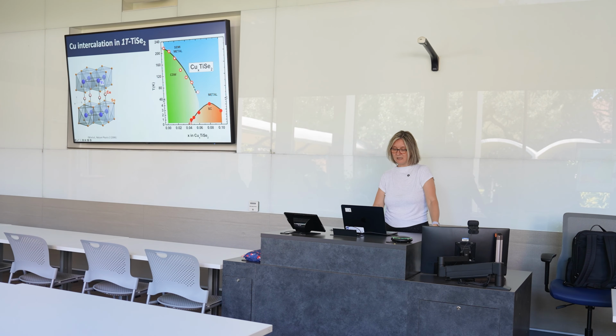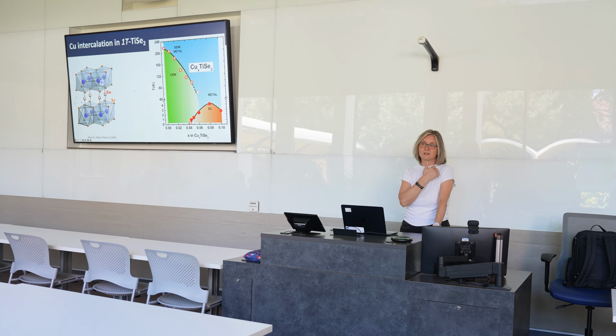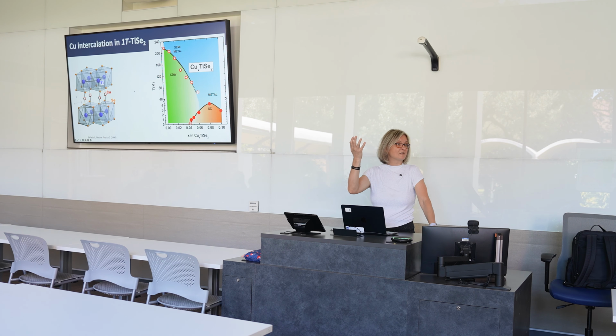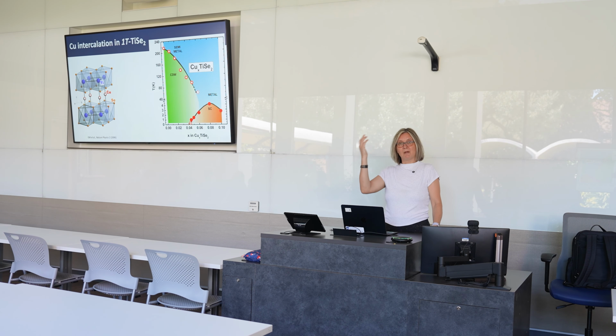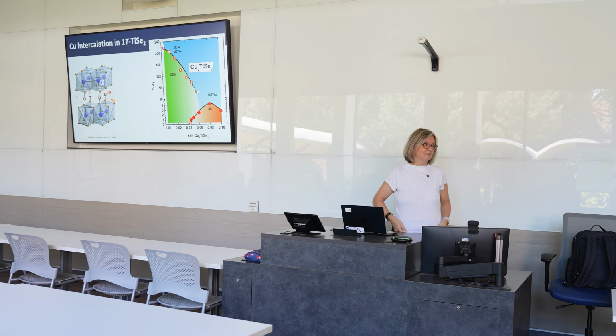And you see here a summary of the charge density wave and the superconductivity. But notice that the superconductivity occurs at very low temperatures, below 4 Kelvin or so. So this phase diagram, for those of you that are familiar with the high temperature superconductors, is very much reminiscent of that in the cuprates, minus the fact that the temperature is nowhere near the high values in the cuprates, right? And for what we understand now, the mechanism is also very different.